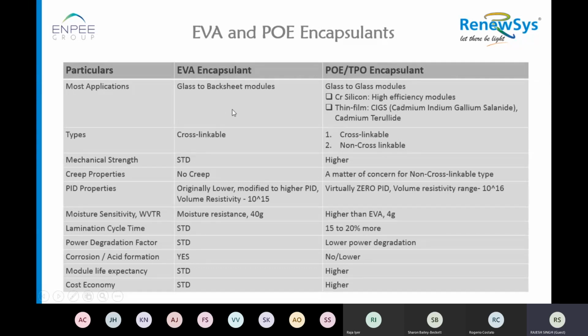So if I do a one-to-one comparison, glass to backsheet is for EVA, whereas TPO or POE can be used for glass to glass. It could be used for crystalline silicon cells, or thin film technology modules, whether for CIGS or for cadmium telluride. These are a few technical names. I hope that we all understand, but any more clarification can be given later. So EVA is a cross-linking type. POE could be cross-linking or non-cross-linking type depending on the structure of the POE during formulation.